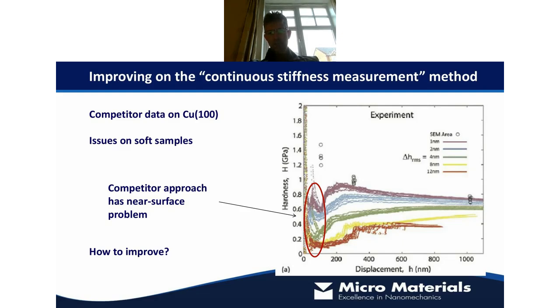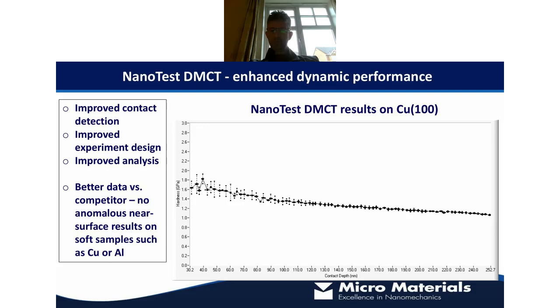So what we're seeing is that as these amplitudes increase, the measurements get more and more silly, and maybe there's probe bouncing, all sorts of things are going on, and particularly in this low load regime, it's not very nice at all. So the standard's pointing you in the direction of saying, well, you could mitigate some of the problems by going to low loads, but it doesn't really suggest that you've necessarily fixed the problem. So this is one of the things that has been bugging us for some time with our own continuous stiffness analog, which we call DMCT, which Jim, our founder, has been working on for a number of years.